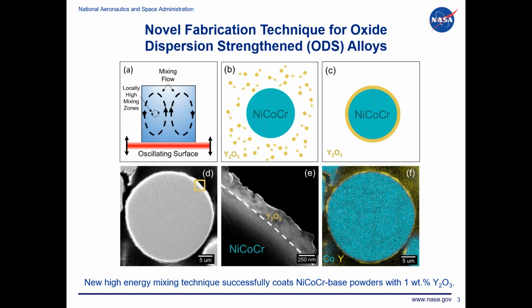So we would mix them together, and during that process, you can see here an SEM cross section of a metal powder. If you really zoom in, you can see this thin layer of yttria that has adhered to the surface of it. And again, in a chemical map, you get this nice highlighted yellow ring around the metal powder. And so our thought was, okay, if we could just coat the metal powder, maybe we can then print it and form an ODS alloy through the printing process.